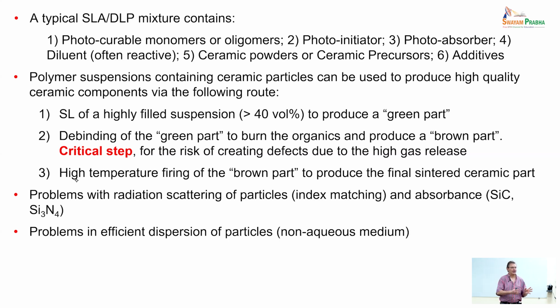So people use highly loaded suspensions, meaning more than 40 volumetric percent. In terms of weight percent, you can go up to 80 weight percent ceramic particle loading into your feedstock. And when you have such highly non-flowable slurries, what you need to do is to have specific printers that spread the layer using a mechanical blade, like a doctor's blade. So in this way, this is the best approach for generating a continuous, homogeneous, flat layer of new feedstock that needs then to be photocross-linked.